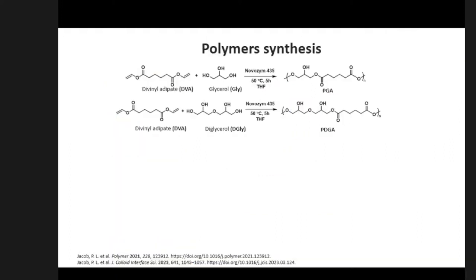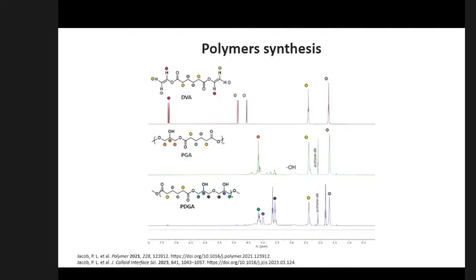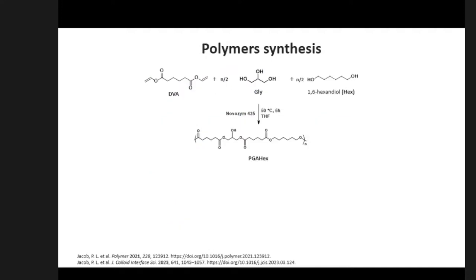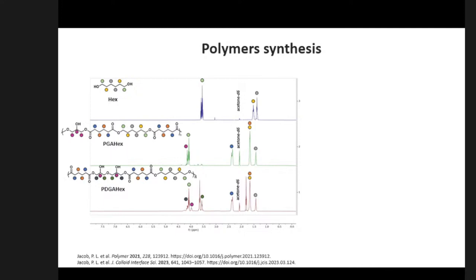Firstly, enzymatic polymerization of PGA and PDGA was carried out using Novozyme as catalyst at 50 degrees for 5 hours, and polymer formation was confirmed by proton NMR. As you can see, the vinyl peaks of the DVA disappeared in the polymer spectra, but also the adipate peaks were broader than before, further confirming polymerization occurrence. The same reaction conditions were used to synthesize the hexanediol-based polymers, and again, proton NMR was used to confirm hexanediol introduction in the polymeric chain.